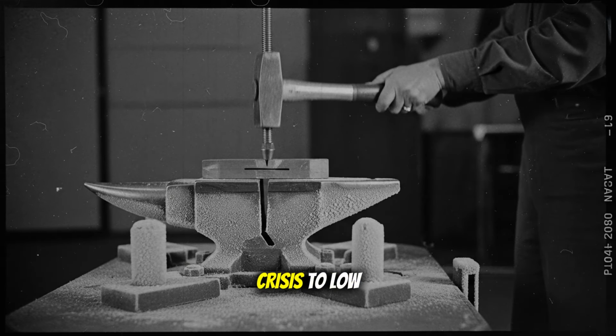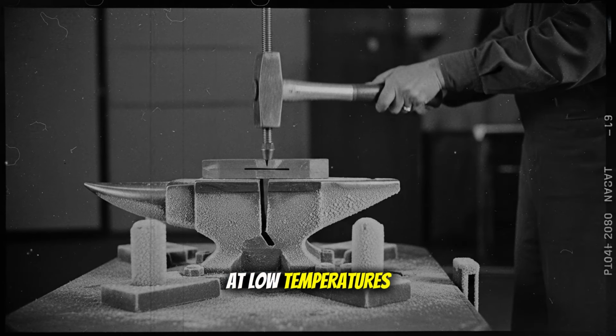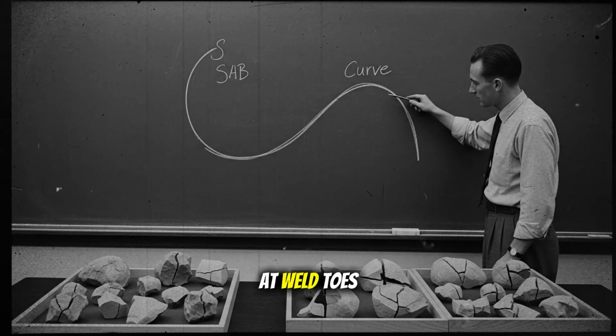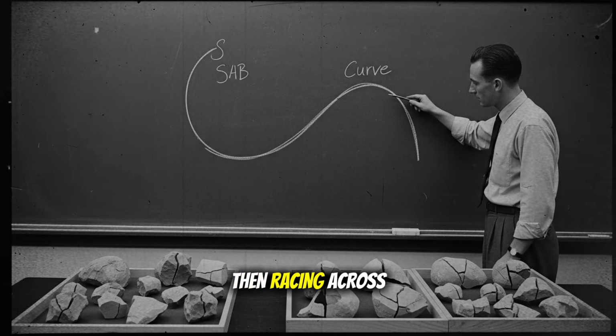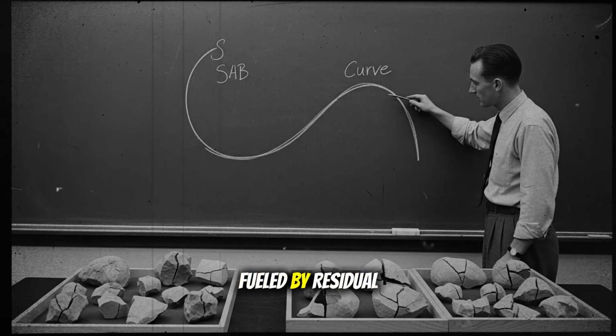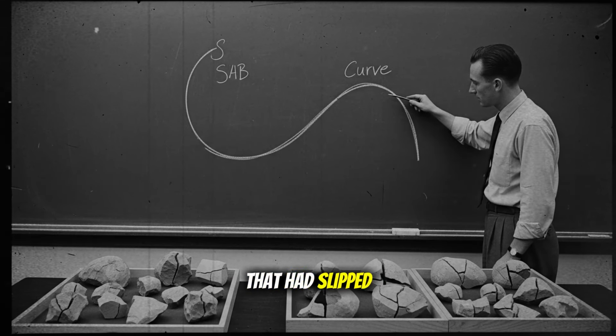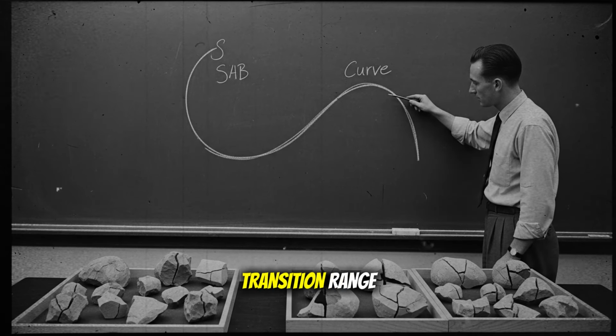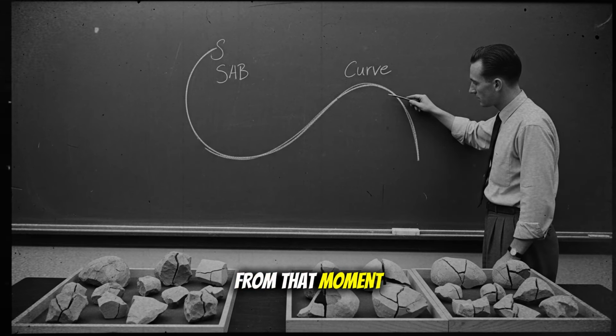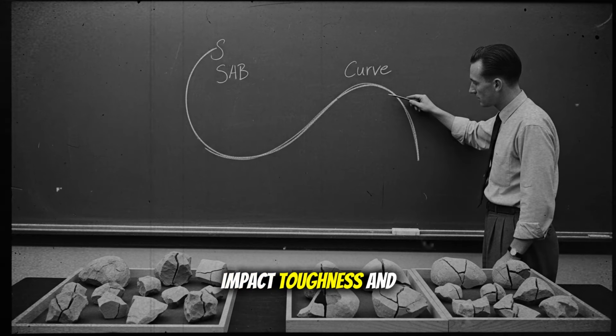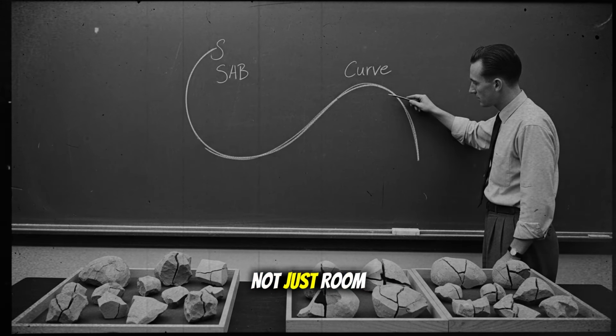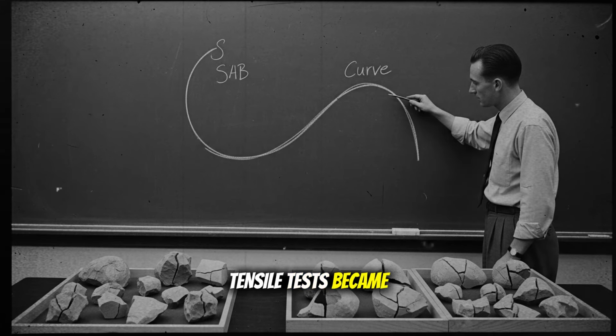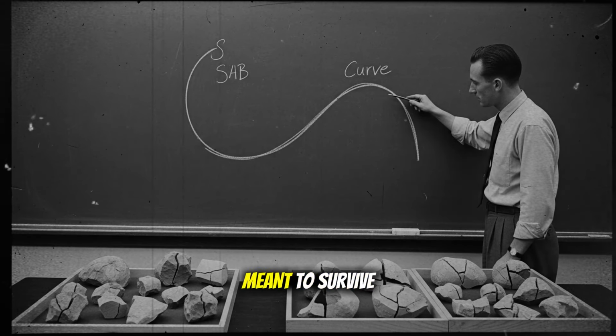Investigators tied the crisis to low-notch toughness at low temperatures, with cracks igniting at weld toes and square corners, then racing across continuous plates fueled by residual stress and a steel that had slipped below its ductile to brittle transition range. From that moment forward, impact toughness and the transition curve, not just room temperature tensile tests, became the compass for any ship steel meant to survive the North Atlantic in February.